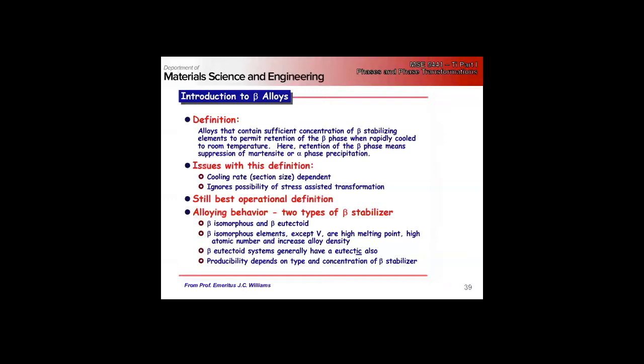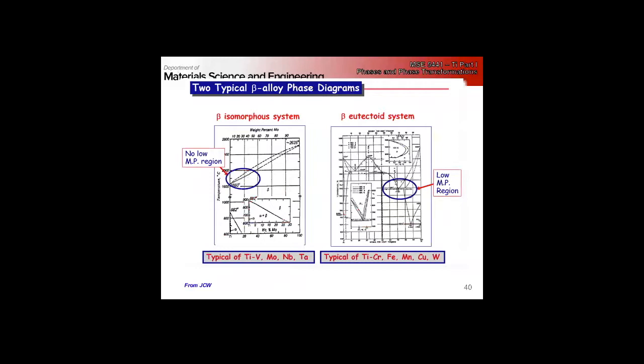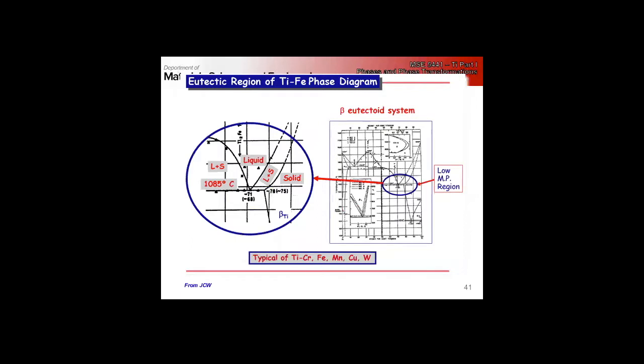And it's just a reminder, we basically have two possible types, isomorphous and eutectoid type beta stabilizers, right? The isomorphous vanadium, molybdenum, niobium, and tantalum are the key ones. Chromium, iron, and tungsten are the key eutectoid ones, right? And here is just a zoom in of the eutectoid phase diagram, the eutectic, right? Liquid directly to beta. Okay.